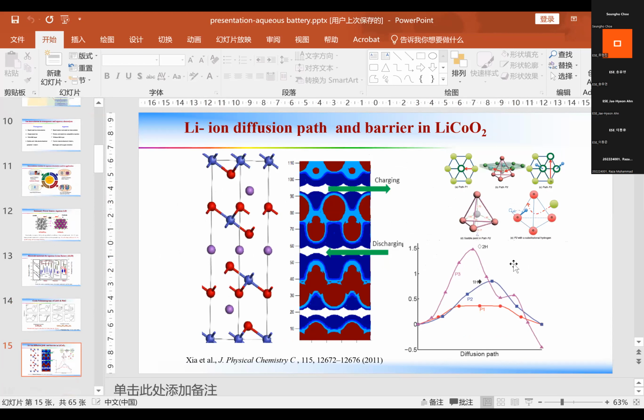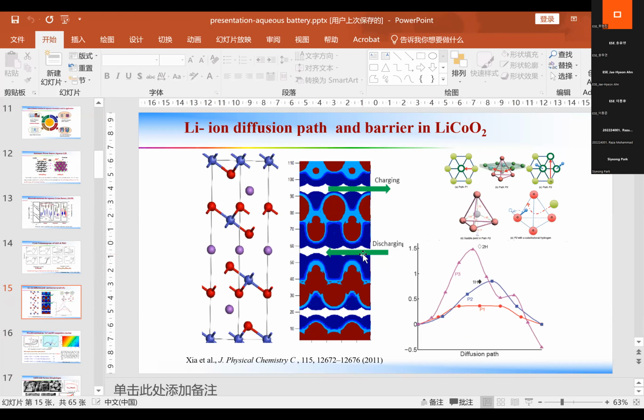So what is happening to this one? At first we applied a simple first-principles calculation to calculate the lithium-ion diffusion paths and barriers of lithium cobalt oxide. The layer structure NMC is similar to the lithium cobalt oxide. Because in the aqueous systems there are protons, if a proton is present at the position of the lithium, the diffusion barrier will become high. This suggests that if protons are present at the lithium positions, because oxygen and hydrogen form a very strong bond, this proton cannot be de-intercalated.